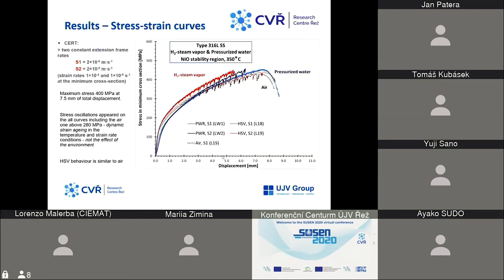And to go straight to the results, here you can see the stress strain curves of our specimens in pressurized water and hydrogenated steam vapor, and also the reference curve in the air. So what we can see is that in the pressurized water, we have a maximum stress of about 400 megapascals, and on all curves we can see those oscillations. We can also see it in the air on the black curve here.